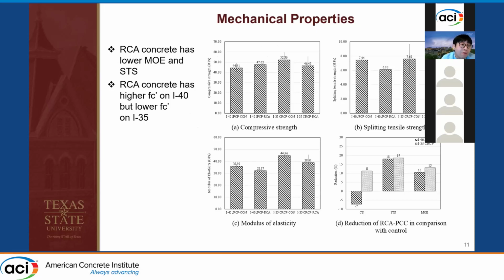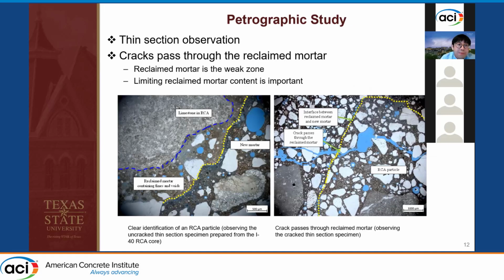For the RCA concrete on the I-40, it had higher compressive strength, but we reported a lower value for the I-35 compared to the control. This is interesting. And we also did some petrographic study. We used a thin section to see the reclaimed mortar, which you can see on the graph here. You can clearly see the reclaimed mortar.